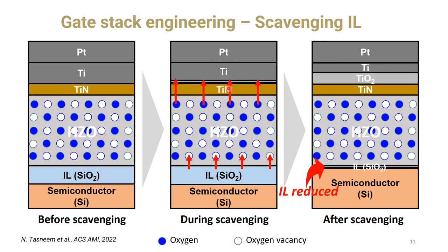On top of the TiN layer, we deposit platinum and titanium, and titanium is a very reactive material. This titanium forms titanium oxide with oxygen atoms. This oxygen atom comes from the silicon oxide IL layer and diffuses through the HZO layer, and it forms a titanium oxide layer above the TiN layer. If this titanium nitride layer is thicker, it's not easy for oxygen to diffuse to the TiN layer. So that's why the TiN 2 nanometer layer is very effective to scavenge the IL and to form the titanium oxide layer.